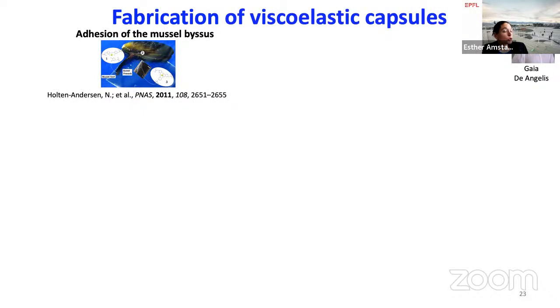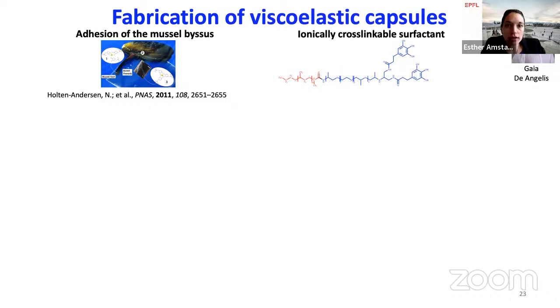Now, this is, again, on individually dispersed capsules. But if you remember what I told you in the very beginning, we actually would like to use these capsules as building blocks to generate more macroscopic materials, okay? But what we also saw is that if you use this first generation of modified surfactants that allow us to form these viscoelastic shells, these shells are relatively weak mechanically, so we can't really up-concentrate them without compromising their integrity and stability. And we could not really control the permeability of them either, because we think they're just too defective.